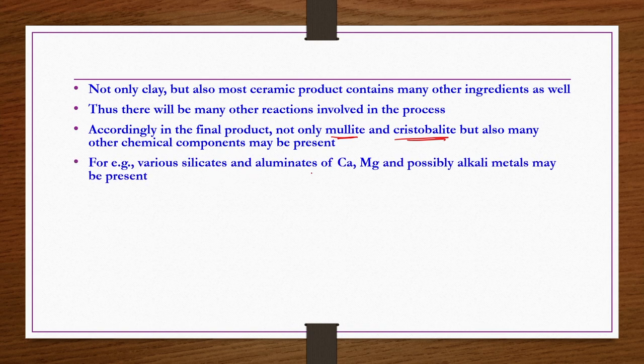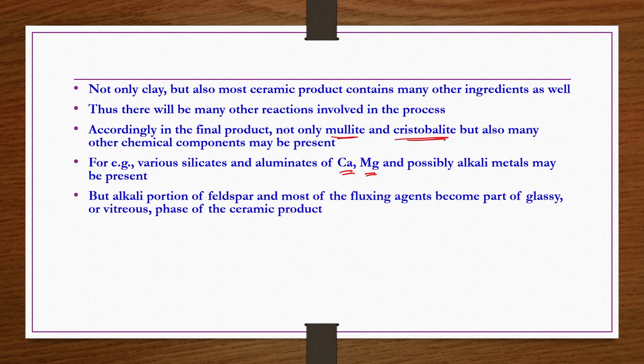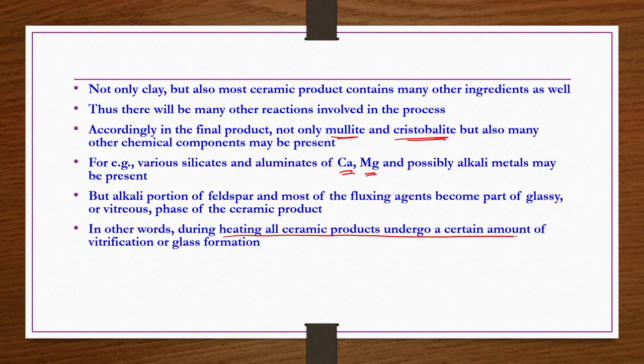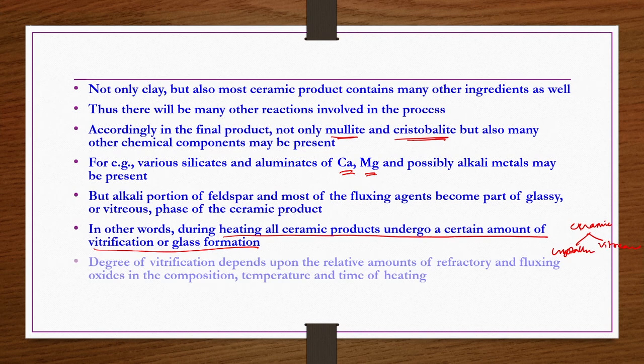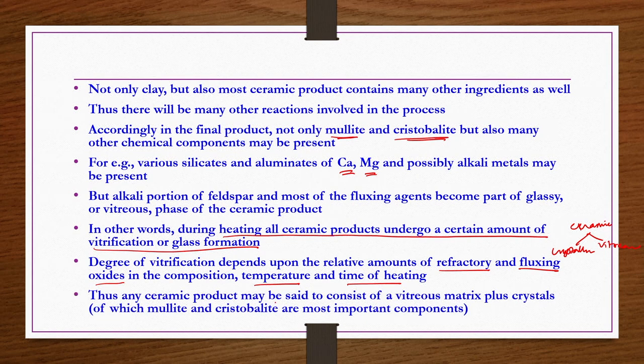For example, various silicates and aluminates of calcium, magnesium and possibly alkali metals may also be present in the final product. Okay? But the alkali portion of feldspar and most of the fluxing agents become part of the glassy or vitreous phase of the ceramic product. In other words, during heating, all ceramic products undergo a certain amount of vitrification or glass formation. So, what do you understand? Ceramic products you can see now as some kind of crystalline material plus some kind of vitreous nature. Okay? So, the degree of vitrification depends upon the relative amounts of refractory and fluxing oxides in the composition and then temperature and time of heating. Thus, any ceramic product may be said to consist of a vitreous matrix plus crystals, of which mullite and cristobalite are the most important components.